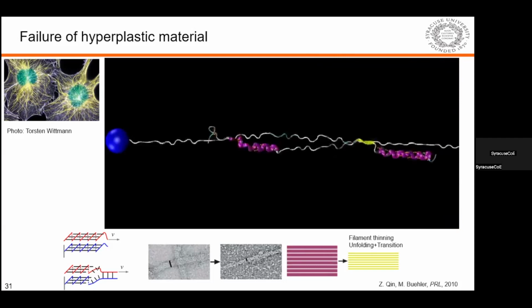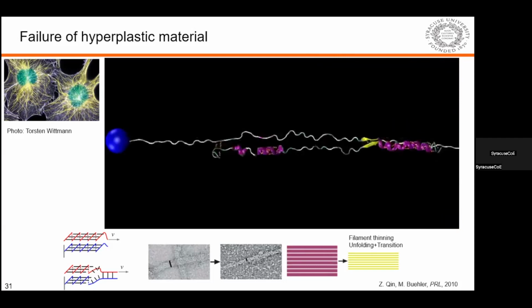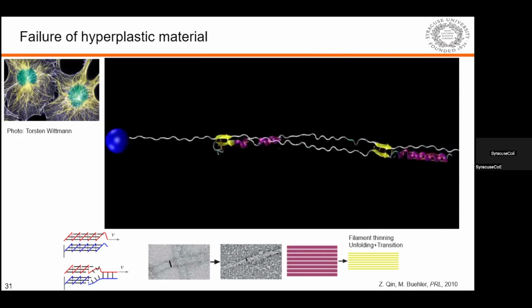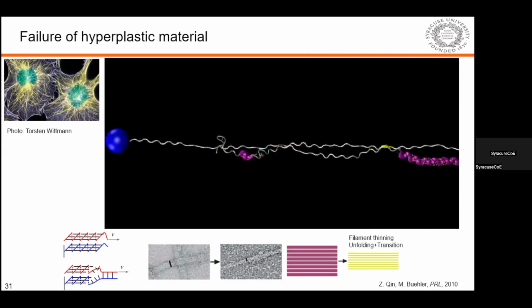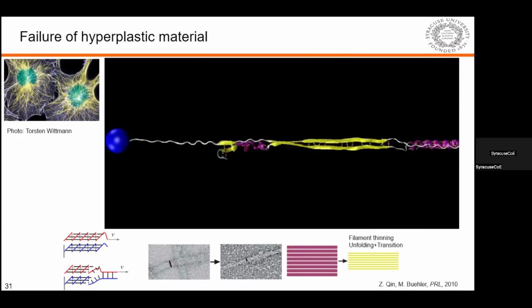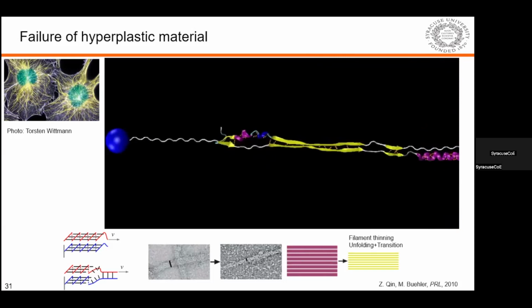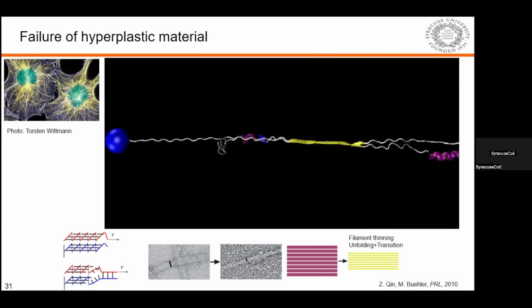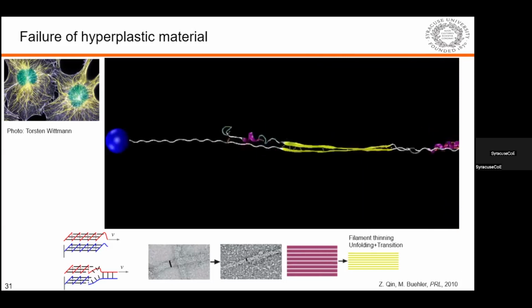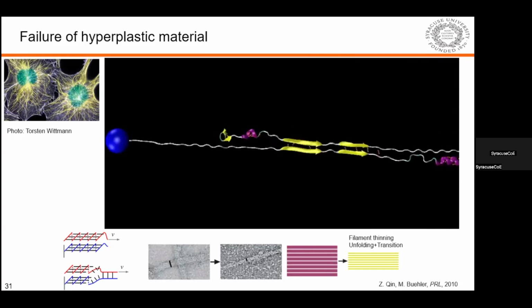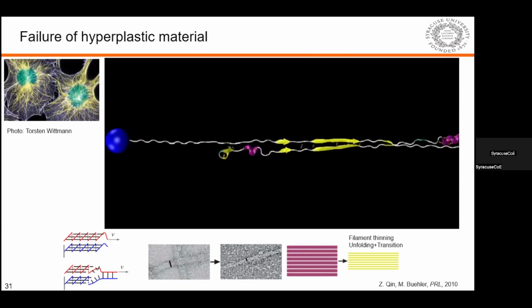Here in my simulation, you see that once you start with the intermediate filament and start applying loading force, at the end it will not fracture. Instead, these alpha helices unfold and transition into beta sheet structure. That significantly contributes to the strength. The alpha helix at the beginning is very flexible, but at the end of the pulling it becomes a stiff material and much more difficult to break.